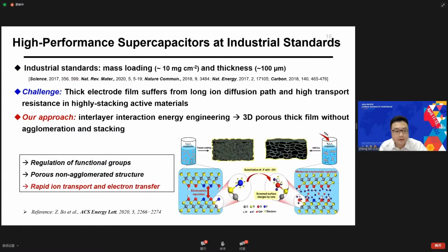Aiming at industrial real applications, a sub-millimeter electrode thickness of 100 micrometers is essentially required. However, the thick electrode film suffers from poor capacity and power density. To address this challenge, we proposed a new strategy of interlayer interaction energy engineering to fabricate three-dimensional porous thick film without obvious agglomeration and stacking.